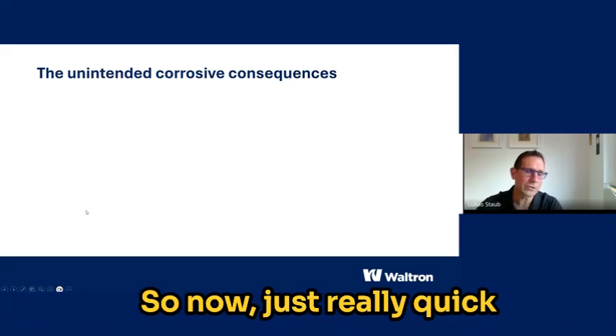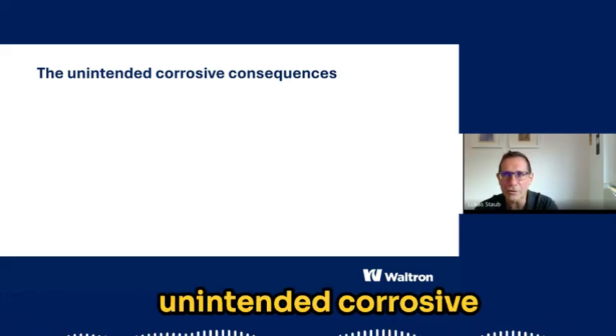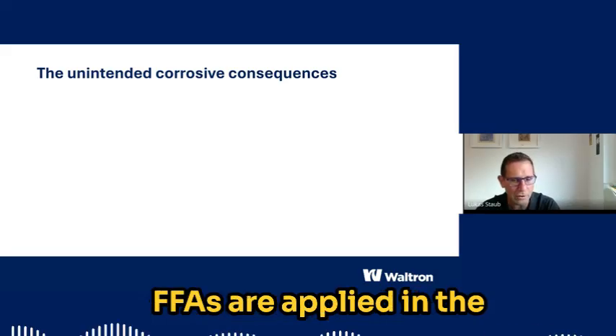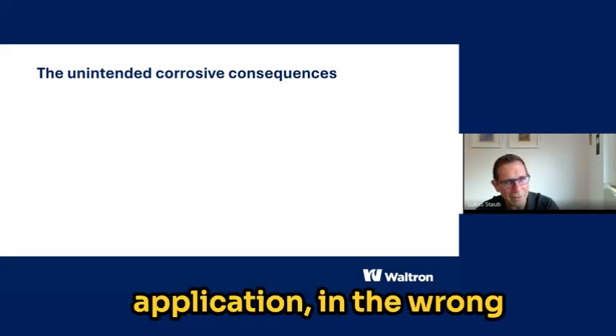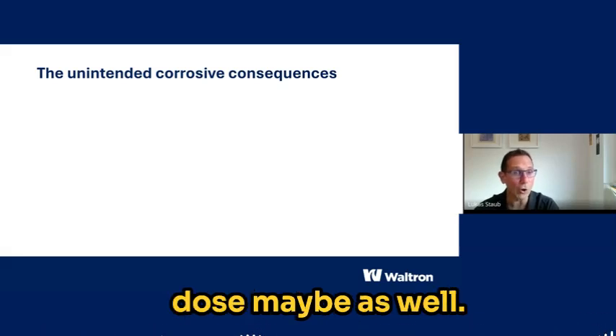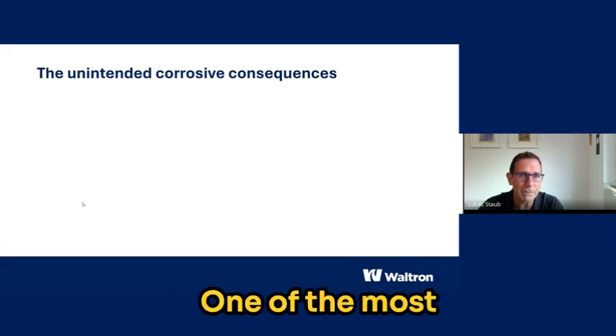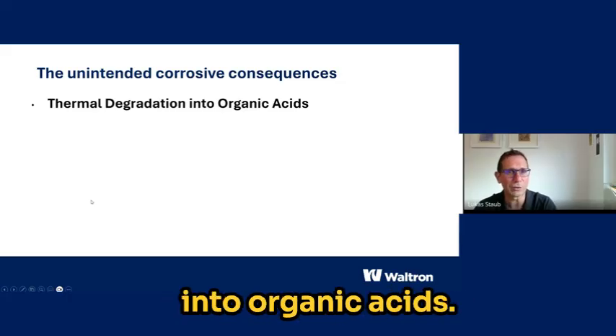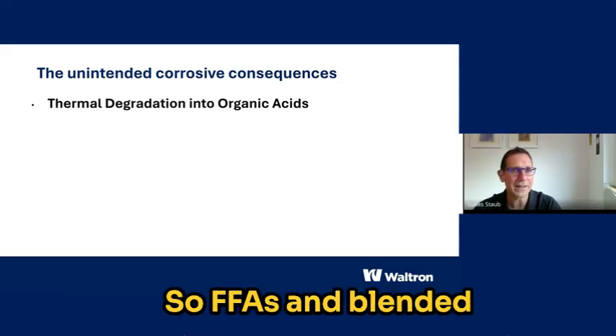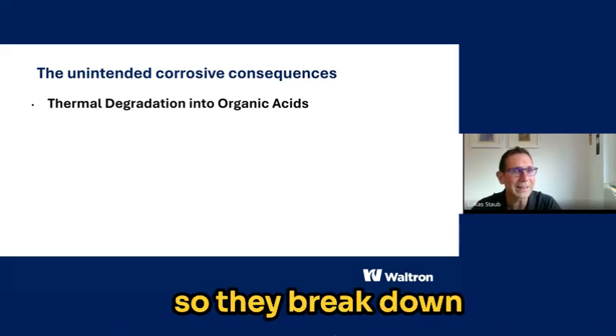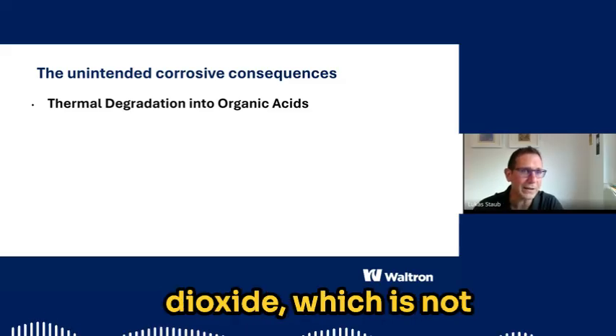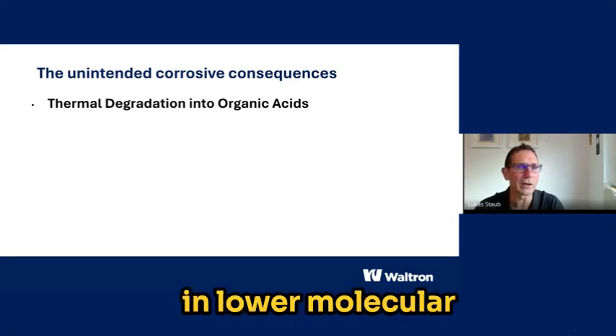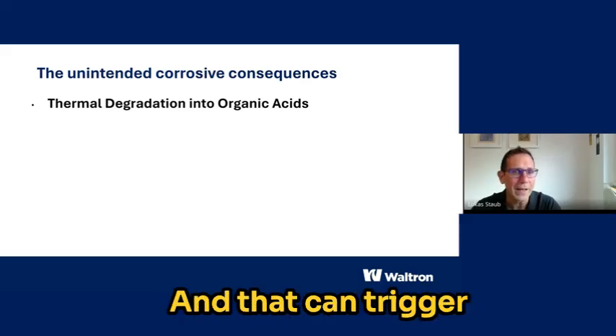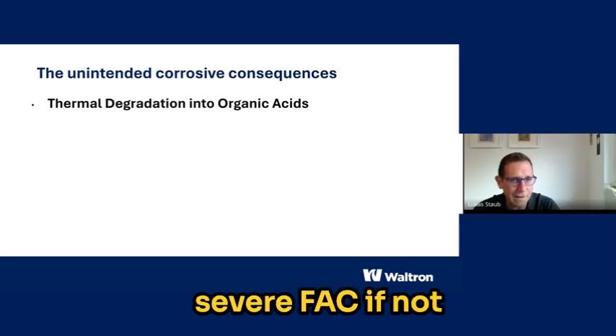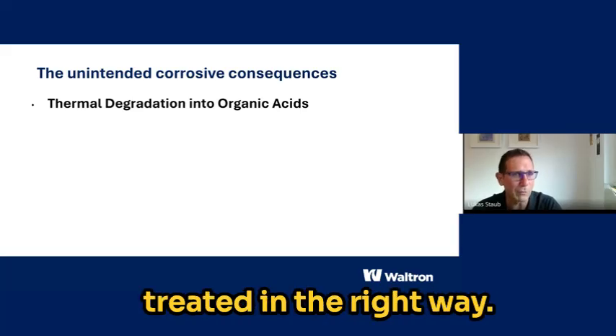So now, just really quick, an overview of the unintended corrosive consequences if those FFAs are applied in the wrong way, in the wrong application, in the wrong plant, in the wrong dose maybe as well. One of the most important ones is the thermal degradation into organic acids. So FFAs and blended alkalizing amines undergo thermolysis, so they break down into carbon dioxide, which is not harmful, but then also into lower molecular weight organic acids. And that can trigger severe FAC if not treated in the right way.